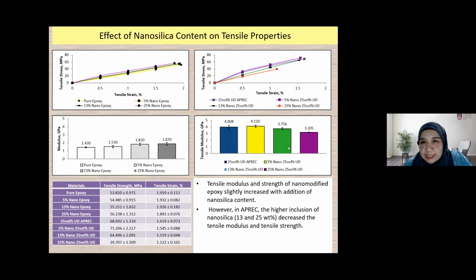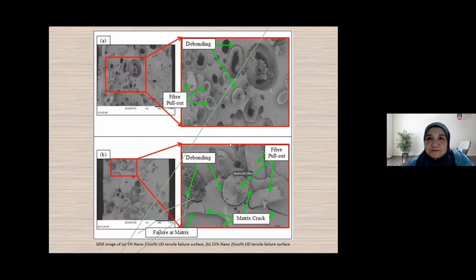For the composite, the best formulation, as we can see here, is for 25 volume percent with the addition of 5% nanosilica. It increases the tensile modulus from 4 to 4.1 GPa. If we increase the nanosilica content, the tensile modulus becomes lower. This is due to a wetting problem in the resin system. So the best formulation for this kind of composite is about 5% nanosilica in 25 volume percent unidirectional Arenga pinnata fiber.